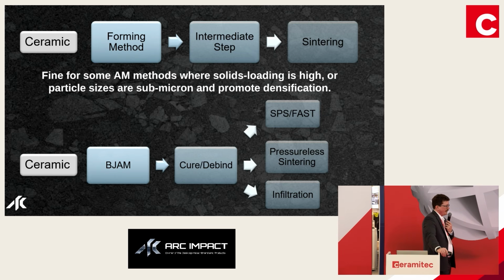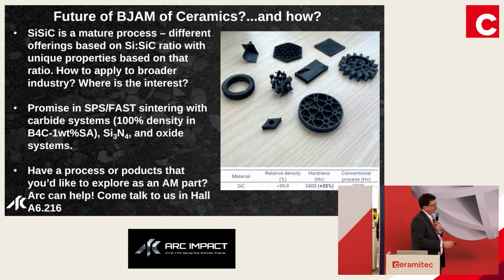SPS has been recently quite effective at fully densifying silicon carbide. You can get away with some pressureless sintering depending on the material system that you're looking at and what sintering aids you have in there. Or you do some sort of infiltration process like the siliconized silicon carbide.